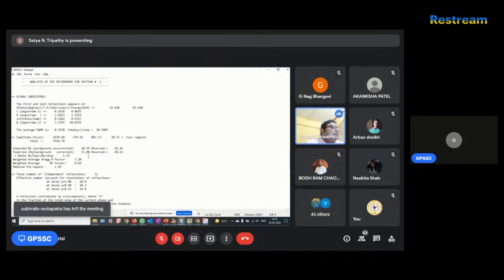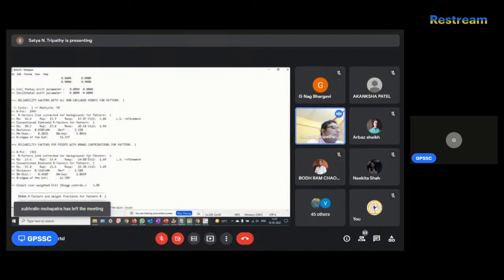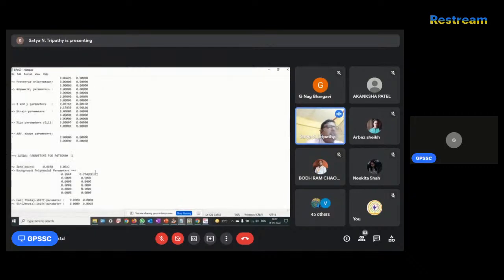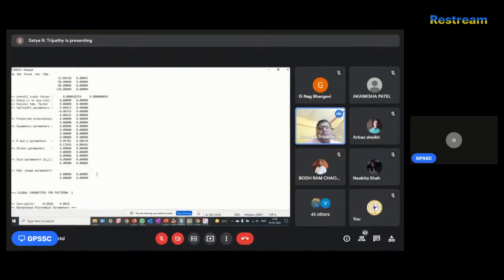Yes, from all this you can calculate your RP and RWP. You can see RP is 13.6 and RWP is 19. Your chi square is 1.69. You can refine more to get a better value.